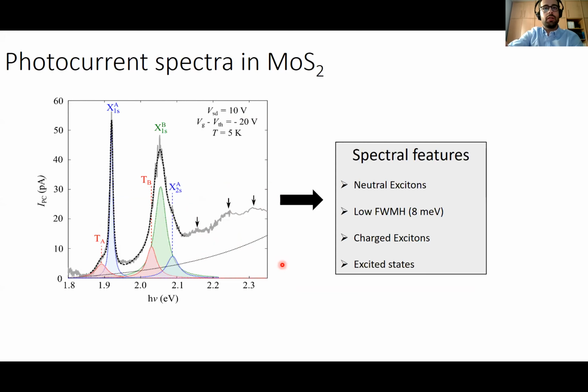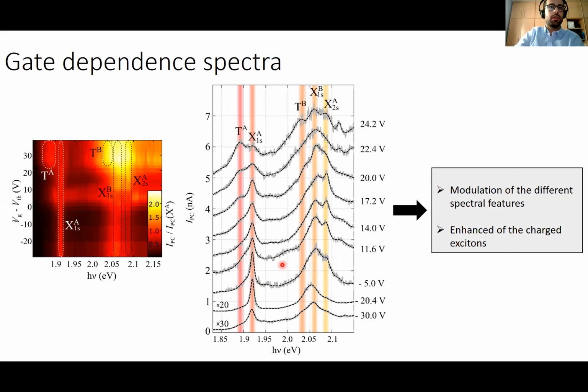These spectra can be modulated by the gate, and this occurs because by modulating the gate we can change the carrier density in the conduction band, and this excess of carriers in the conduction band can produce efficient formation of charged excitons because we have a lot of electrons. So here we can observe that trion A is enhanced as a function of the increase of the gate. Here for the trion B we observe the same behavior, and the excited states also can be changed using the backgate voltage.